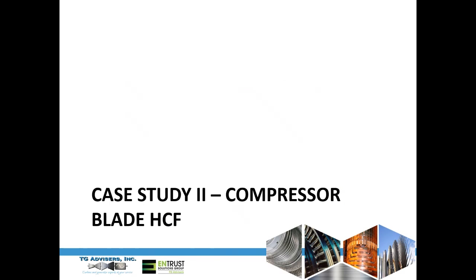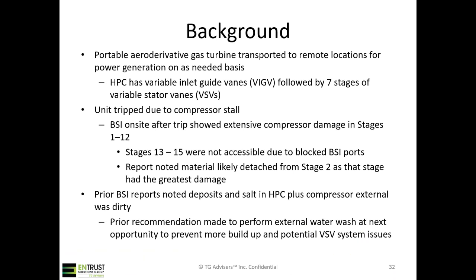The second case study here is looking at compressor blade failure. So for this compressor blade failure that we investigated, it was an aeroderivative gas turbine. It's portable, transported to remote locations. The high pressure compressor section has what's called variable inlet guide vanes, followed by 7 stages of variable stator vanes. So all of those vanes can rotate depending on the speed of the engine. The unit tripped during operation due to a compressor stall event, and a borescope conducted on site showed extensive damage throughout stages 1 to 12, and then stages 13 to 15 were not accessible due to blocked borescope ports. But that borescope report noted material likely detached from stage 2, as that stage seemed to have the greatest damage.